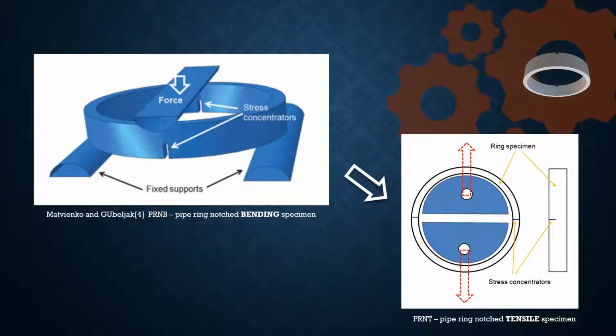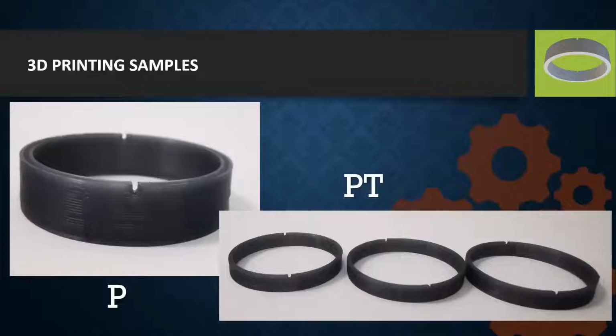However, it can be said that loading in bending is not ideal for simulating the load of a pipeline. Therefore, the geometry of the ring, but loaded with tension, is considered in this study. The first step in this study and in the development of this experiment will enable us to obtain fracture mechanics parameters from ring-shaped specimens with a crack.